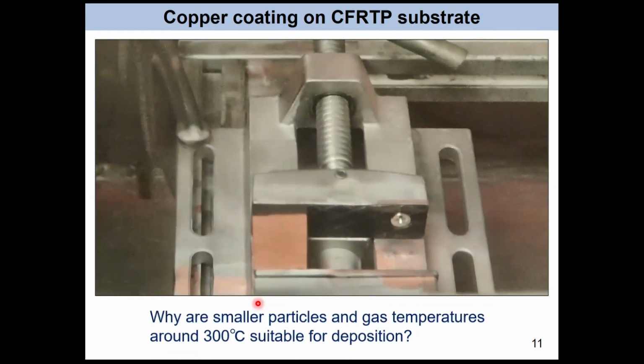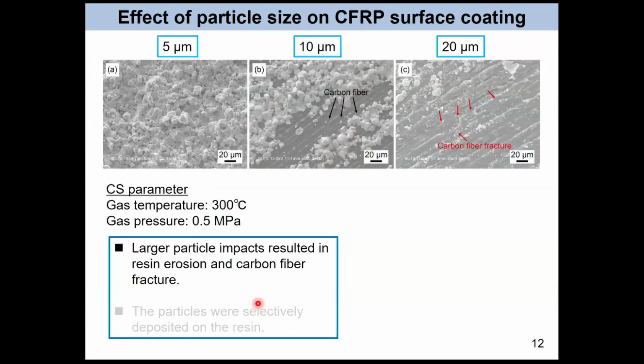But why are smaller particles, in this case 5 micrometer particles, and gas temperature around 300 degrees suitable for deposition? We have to analyze this point. First, we observed the surface SEM image for each particle size, and we can see the continuous coating when using the 5 micrometers. But in the case of 10 micron and 20 micron, the coating is not continuous, and now we can see the resin part. The CFRP is composed of resin and carbon fiber, and the resin part is removed by the impact of the 10 micron particles.